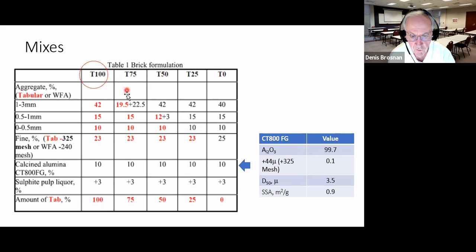Now they made some other mixes at lower percent tab alumina, and then they made one with only a very small or negligible amount of tab alumina, a little bit of calcined alumina here. I think they used white fused alumina fines here. And so, again, they were using the CT800FG to encourage sintering.